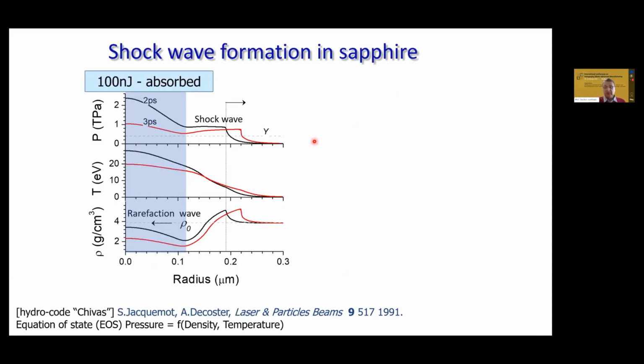Once we know the energy absorbed in the volume, we can calculate by equation of state how the pressure, temperature, and density evolve in time for the absorbed energy deposited in the volume, which for the simulations was considered spherical. In this volume, the energy of 100 nanojoules will drive pressures. You see the times. The light is already gone, so this is the evolution of modification of the material. There is formation of a shock wave. The Young's modulus is the dashed line, so you see that the shock wave is well above the Young's modulus of the material. This is why we can create strong modifications.